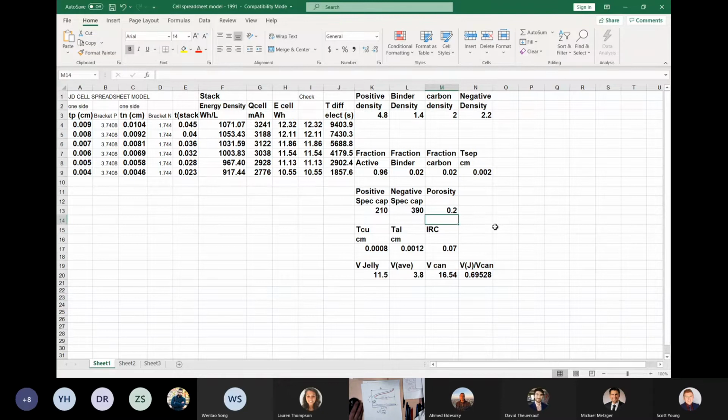And then if you go out and you actually measure the can of an 18650 cell, you'll find they're not 18 millimeter diameter. They're more like 18.6 millimeter diameter. So people are cheating every way they can. So this radius has to be increased to 0.93.